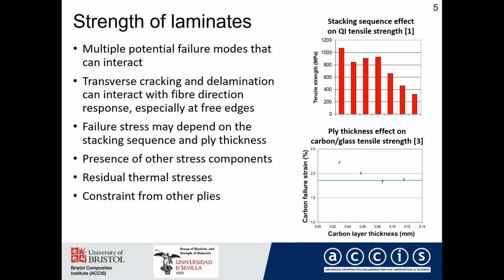Now, when we come on to laminates, it's a whole different question, very much more complex, because in laminates, you have multiple potential failure modes that can interact. You've got transverse cracking and delamination, which can interact with the fiber direction response, especially at the free edge. So this top right shows some results which we did some years ago on different stacking sequences. So these are all quasi-isotropic tensile strength tests of the same size specimens, but you see there's a huge variation in strength just because of different stacking sequences and different ply block thicknesses. So it's not enough to say the strength of a quasi-isotropic laminate because you can get almost any value depending on these different parameters.